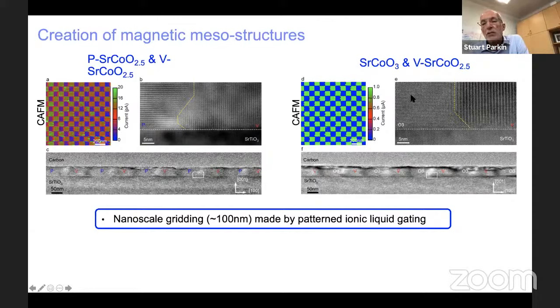And on the right-hand side, we have a boundary between a metallic ferromagnetic perovskite and this antiferromagnetic insulator. And you can see this in the cross-section TEM. So we can actually make a wide variety of spatial magnetic mesostructures this way. We can even make a racetrack out of this strontium cobalt oxide SrCoO2.5, with a metallic SrCoO3 stripe, and see the domain walls move. And it turns out they move extremely efficiently.